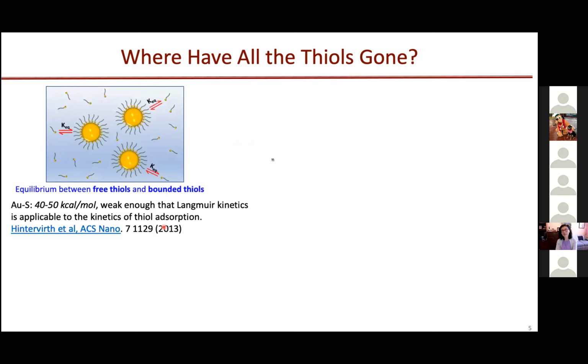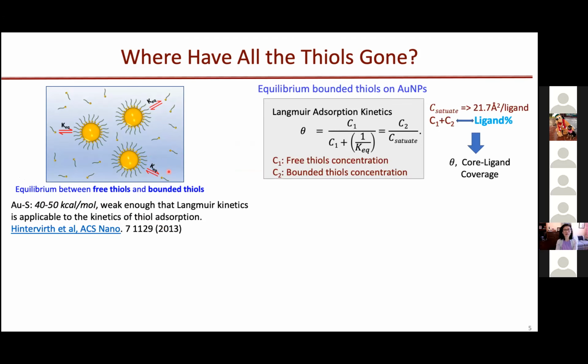So another theory is that the gold-thiol bond is actually not that strong—weak enough that bonded thiols can fall off, forming an equilibrium exchange with free thiols. This process can be approximated by Langmuir adsorption kinetics.